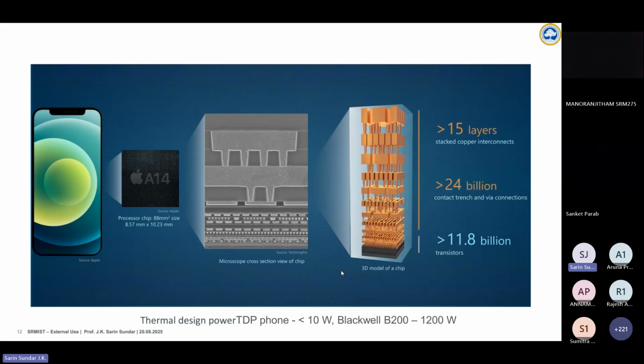So we also see here another slide where we talk about the interconnects, right? This is the same picture from the last slide, but we really focus on the back end of line interconnects, and there you have about 15 layers typically for the A14, and today it can go up to 19 layers. And today there are also new design architectures where they are using backside power delivery, or the power delivery is taken on a separate chip and bonded together. And this has more than 24 billion contact trenches and via connections. So as you see, there are a lot of patterning requirements, and patterning requirements, especially the lithography, are one of the primary sources of defects also.